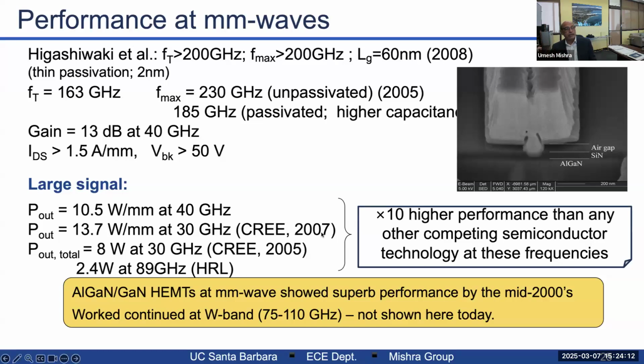So what ended up happening is we basically said, instead of arguing against some theory, just make the damn devices. Thanks to Harry Dietrich at ONR and others, they gave us money to do this, and we showed that we could get 10 watts per millimeter at 40 gigahertz. And that kind of retired the naysayers who thought that gallium nitride, because of this hot phonon business, would be a 10 gigahertz technology. And in fact, at that time, there was some early work that also showed 2.4 watts total, sorry, with multiple chips at HRL. And I'm talking about a long time ago.